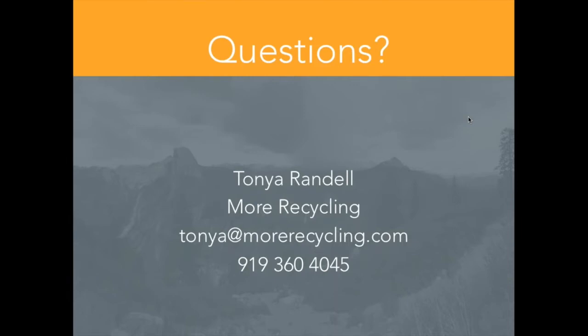For anyone who's never been to a MRF, the material is going by really quickly. There's lots of different materials in there. So, for example, out of a MRF stream, you may see that the PET bottle bale has a lot more thermoforms in it because you're seeing a lot more thermoforms, but you're also going to see bits of paper, or bits of cardboard, or shredded paper that's been intermingled just because of the way that it's being processed. And so that bale yield that I mentioned, 60 to 70% for PET bottle bales, is predominantly from single stream materials. So obviously, as you get to dual stream or source separated, where the bottles are kept separate, the yields go up.